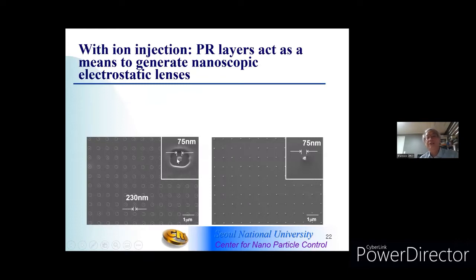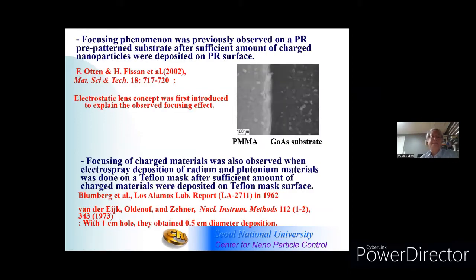Particles are only deposited at the center of the opening area due to the generation of the electrostatic lens caused by ion accumulation. You see 75 nanometer, but I want to emphasize that 75 nanometer is not a single particle, but multiple deposition of 10 nanometer silver particles. And if you eliminate photoresist, then you obtain well-aligned, nanometer scale nanoparticle patterns.